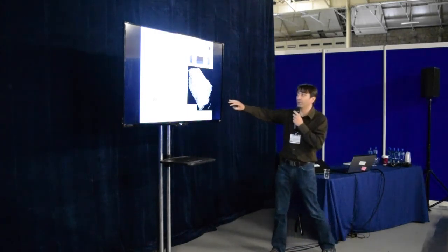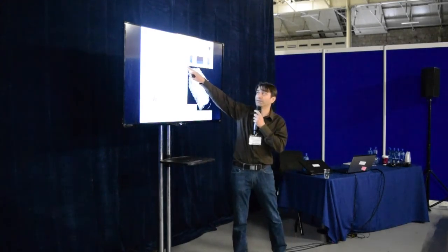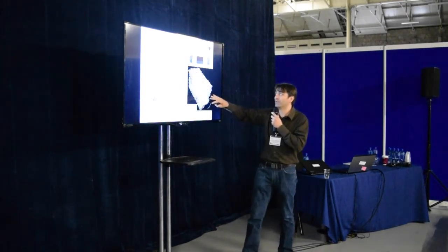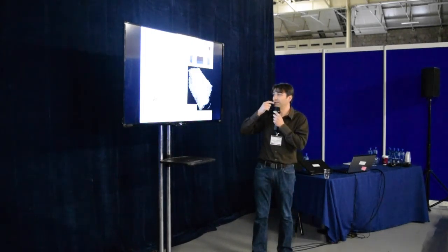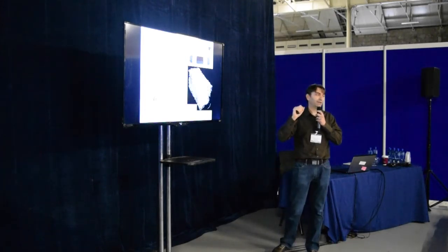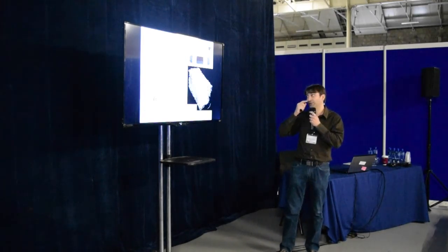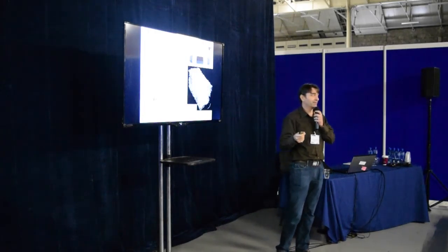This is how it actually looks, the distribution of the steel fibers in the mix itself. But we can also use graphite. The only advantage of steel fibers is that they have better conductivity, so they can conduct the electrical energy better, and also they can introduce higher strength of the material, so increase the strength of the material.